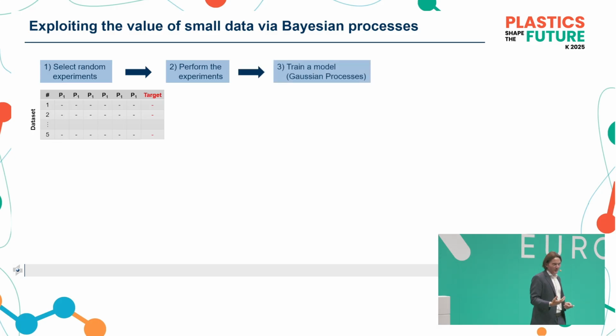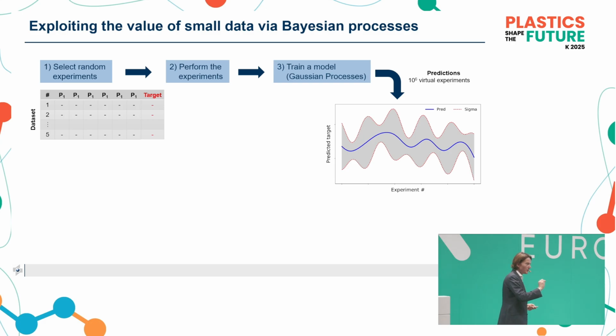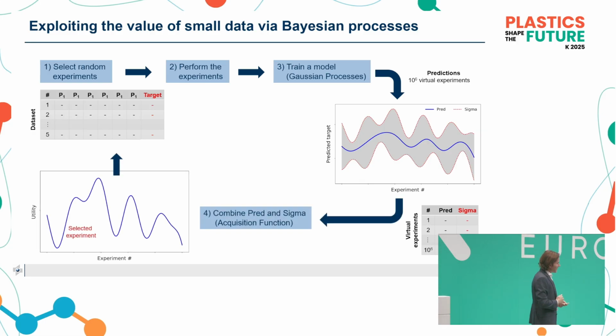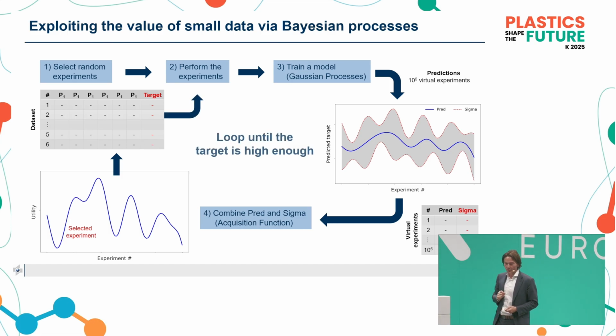Based on these very few experiments, you train a model. It will not be a good one, but it's a good starting point. Subsequently, you perform virtual experiments. So based on your poor model, you calculate 10 to the power 6 different variations of these processing parameters. So you predict also the properties, which you assume with a certain uncertainty. You evaluate which trial you have not taken yet gives you the maximum output, making your model better or optimizing your properties. You do the next experiment with a selected set of parameters. You perform the experiment and you loop until you end up with the desired quality of the data or with a high accuracy of the prediction model.